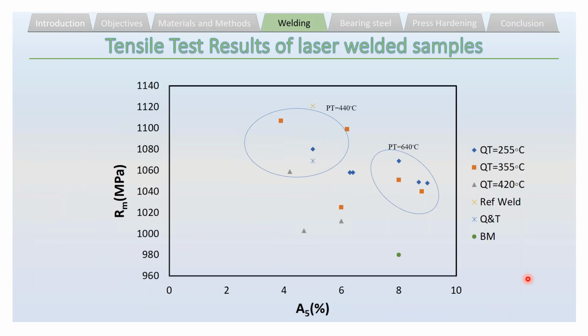Here you can see the tensile test results from the laser welding and quenching and partitioning afterwards in different conditions. You can see that all of them have higher strength than the base metal, and in some of them we have the same ductility or even higher. For example, at 440 the partitioning temperature was not high enough, so it's almost the same as a reference weld, just as welded, and quench and tempered condition.